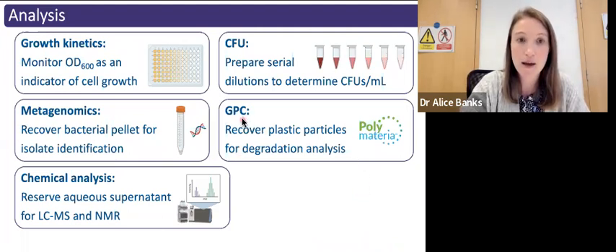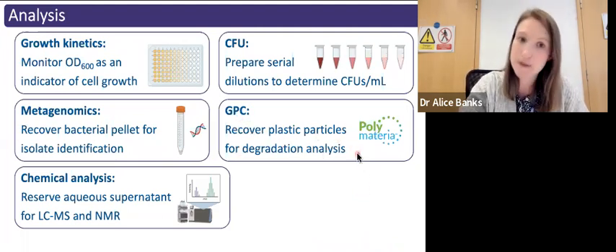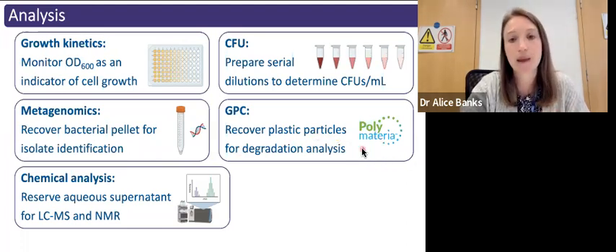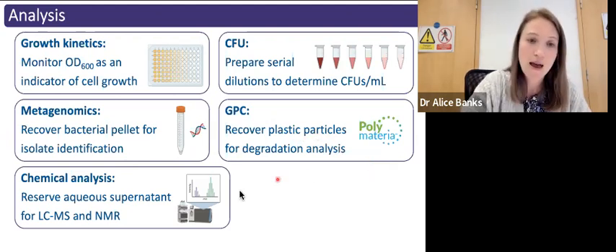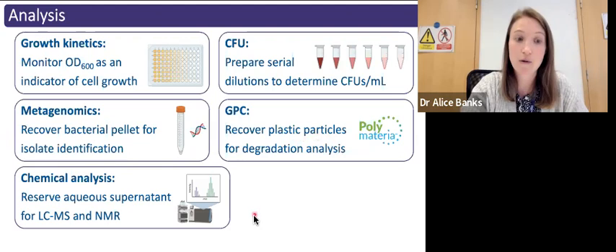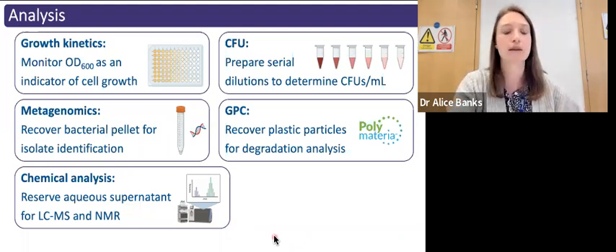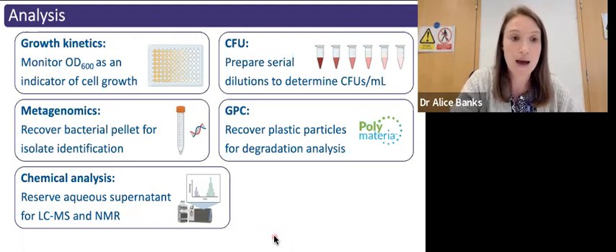And by recovering the plastic particles, they can be sent to Polymateria in collaboration, and Polymateria will conduct the GPC analysis, and this will show how the polymer changes over time. And finally, chemical analysis is likely to involve LCMS and NMR, and we hope that this will assist us in identifying any water-soluble intermediate products that are present in the supernatant of our samples. By identifying the intermediates, that should give an indication as to the type of genetic or enzymatic mechanisms which are at play, allowing that degradation.